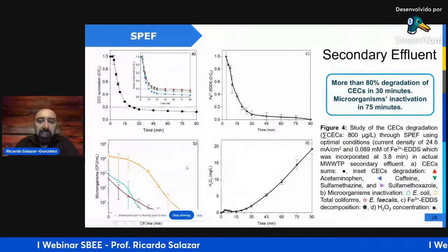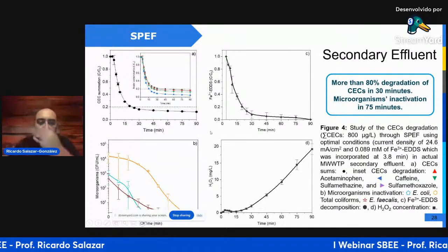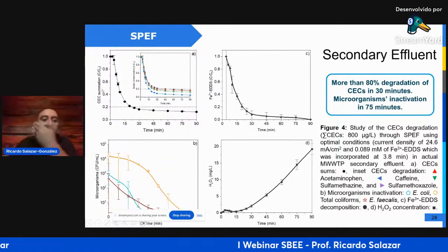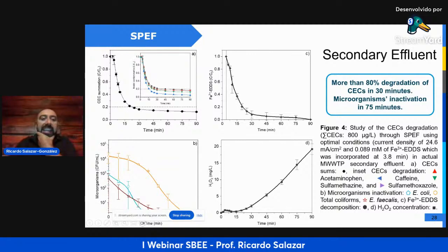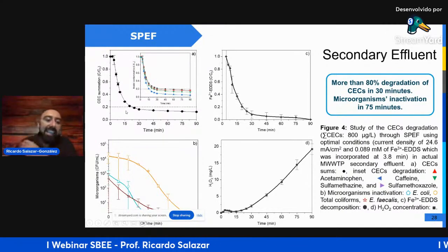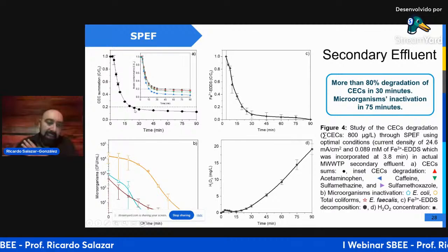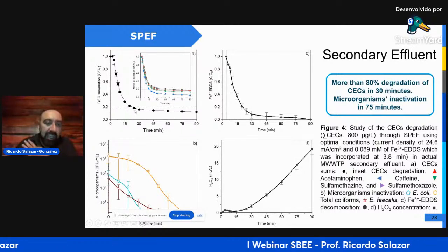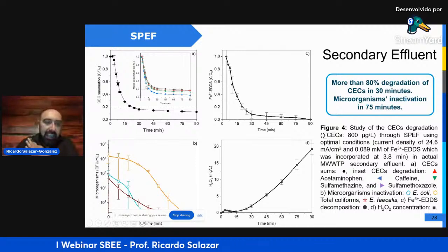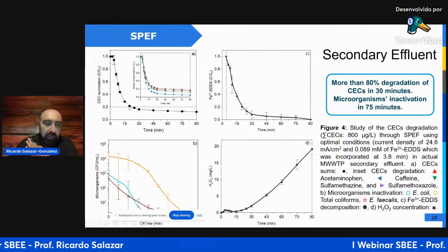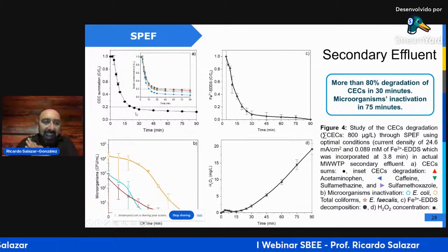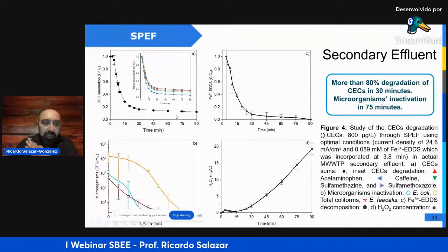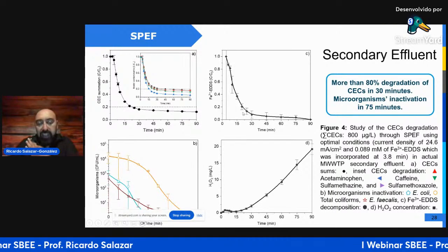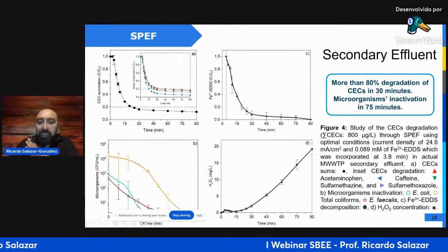So the treatment of a secondary effluent containing these contaminants of emerging concern showed complete or more than 80% degradation of the pollutants before 30 minutes. This is each pollutant. Here is the mixture of pollutants. And the decay of the concentration of the pollutant occurs at the same time as the decay of the concentration of the complex during the process.